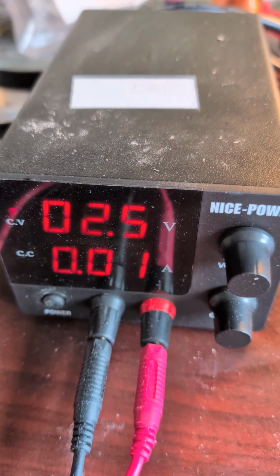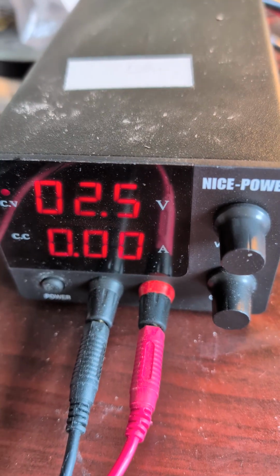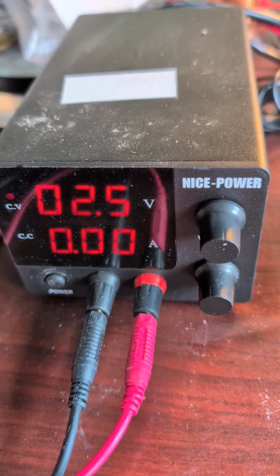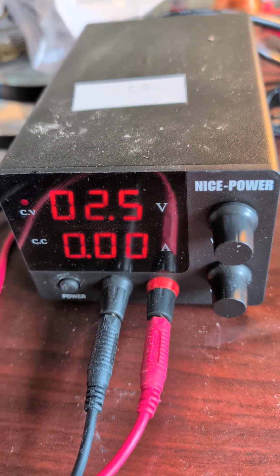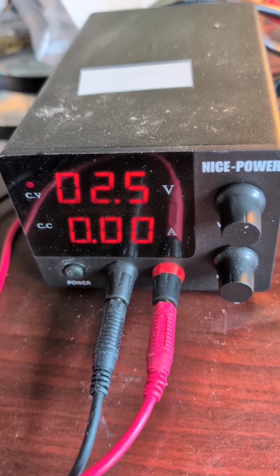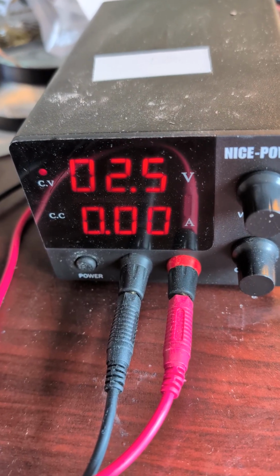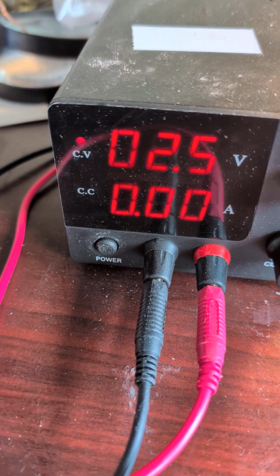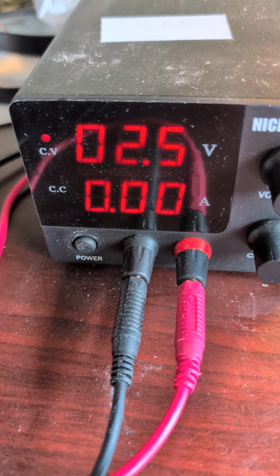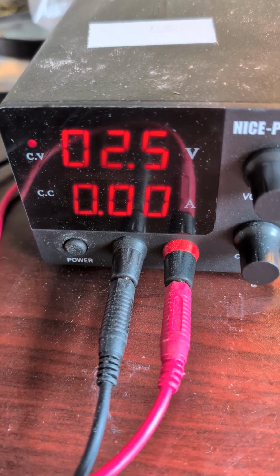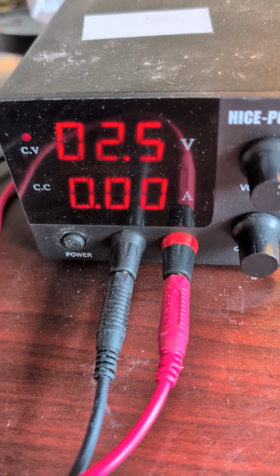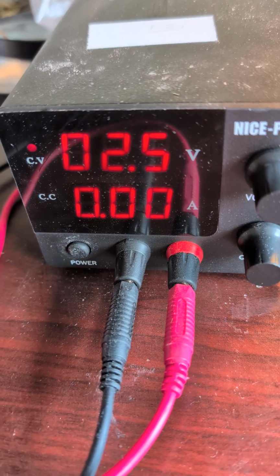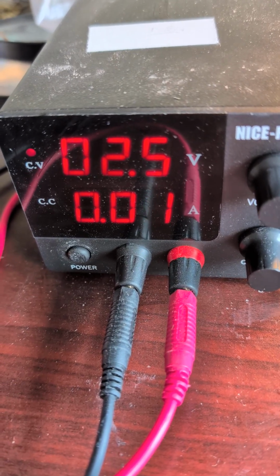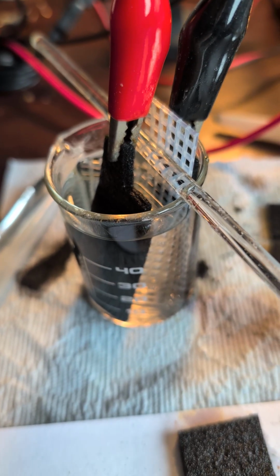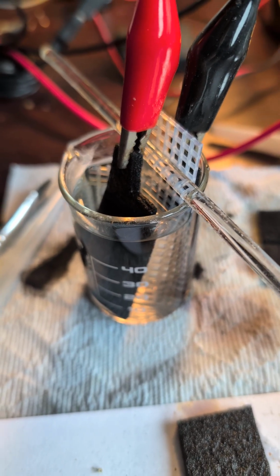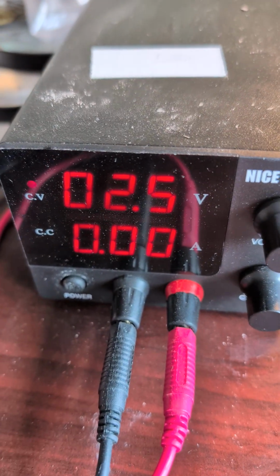And right now, 2.5 volts. And my DC power supply here, which is very cost effective, I got it on Amazon. For me, it was about $35 US dollars, and I don't pay postage here. And 2.5 volts, constant voltage is being applied by the power supply. And the current is vacillating between 0 amps and 10 milliamps. So let's say I'm seeing about 5 milliamps. I'm still not at equilibrium. This has been running about a half an hour. No gas evolution being observed. And that's exactly what I want. 2.5 volts would be just fine.